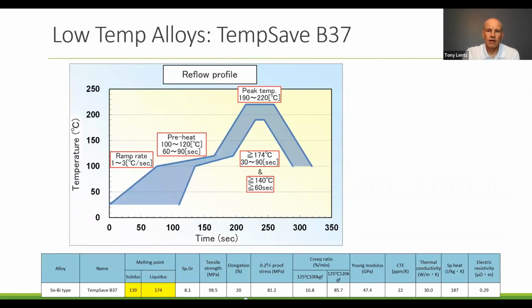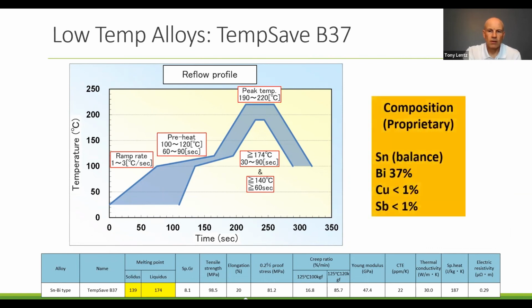Here's a little bit of data on the profile used for TempSave B37. So B37 is designed as a low melting alloy that outperforms traditional tin bismuth 58 and tin bismuth 57 with silver. The composition is proprietary, but it's based on tin with 37% bismuth and some additives. The melting range is 139 to 174 C. So it actually melts approximately 10 degrees cooler than tin lead solder.